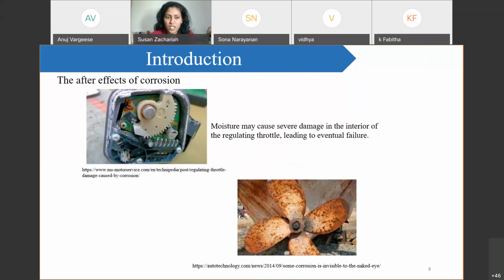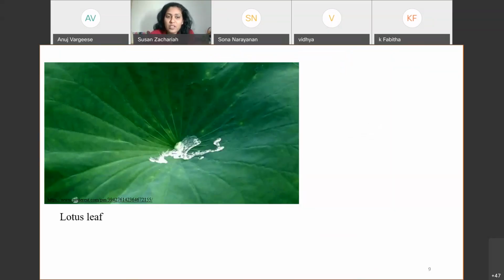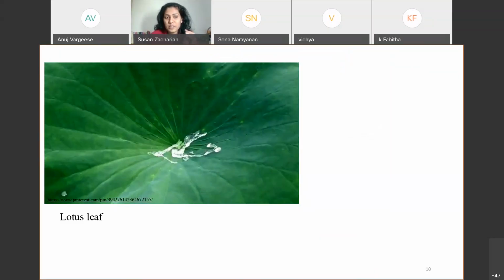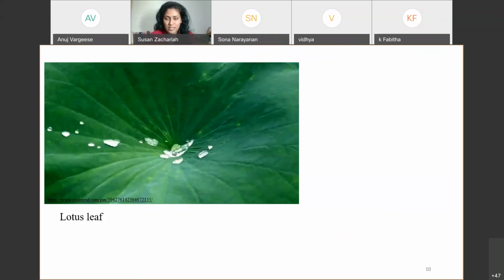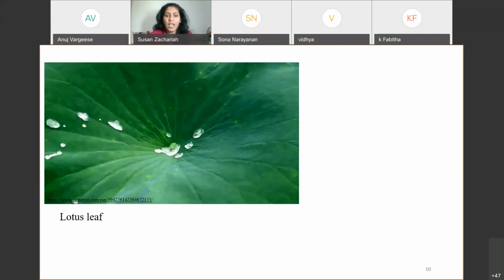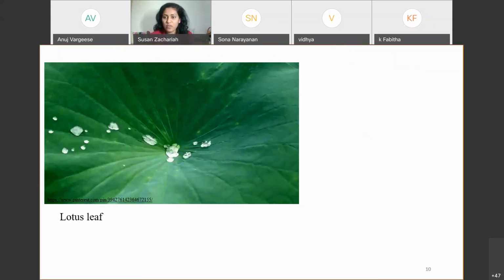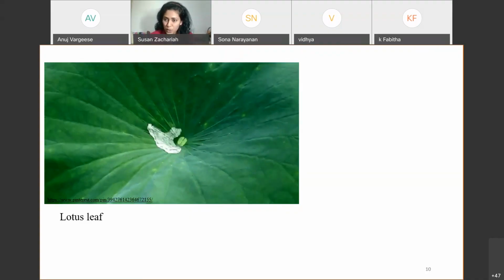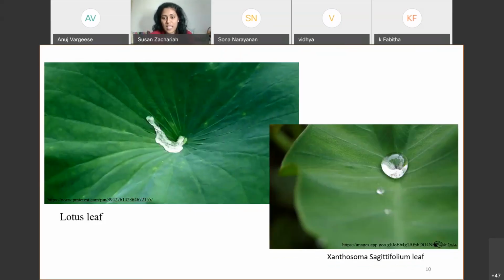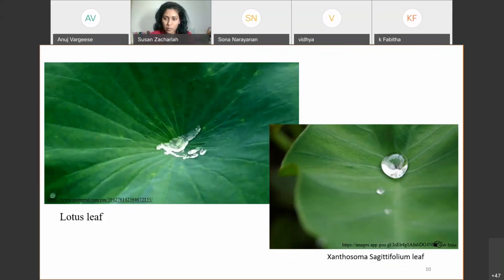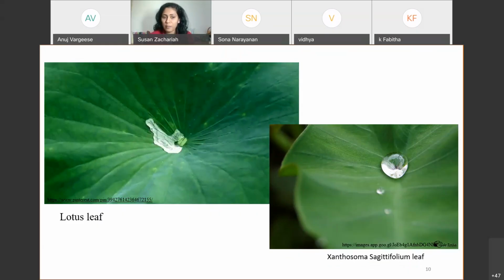These are some pictures that show the corroded particles that cause problems in your applications. If we can avoid the presence of water and air, then it is easy for us to control the corrosion. This is an animation to show how a lotus leaf acts when we drop water on it. Due to the nanostructures, the nanopillars on the surface, the lotus leaf has a high contact angle and repels the water. Whenever we pour water on the surface, it rolls off and cleans the surface. I used the lotus leaf and also another leaf called Xanthosoma sagittifolium, which also showed the same property of superhydrophobicity. In my work, I have compared both leaves.